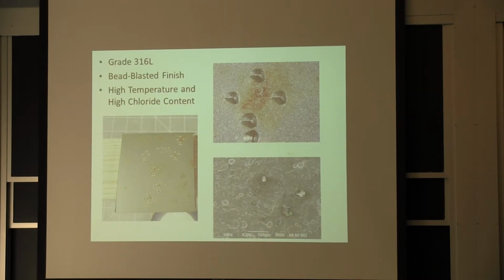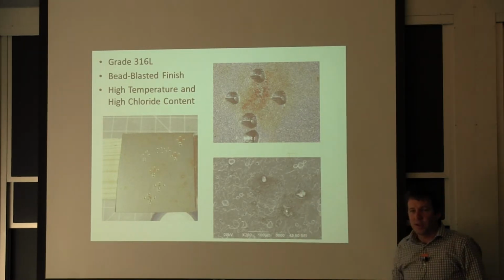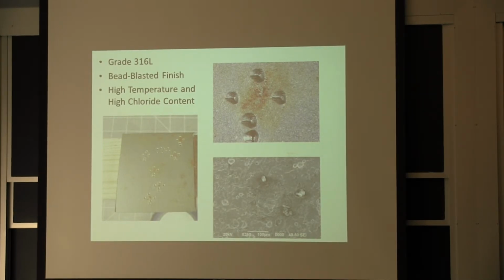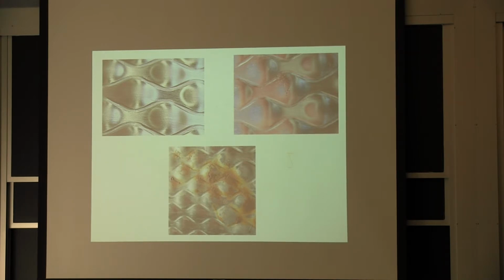This is a more severe issue, these plates. You can see one side wasn't worked on. They were using beads to make a special finish, a kind of satin finish, on the stainless steel. But the beads were so small and provided at high energy that it was creating holes, and they were remaining embedded on the surface, and that caused the initiation of the pitting reaction. And then from there, it just starts growing to a macroscopic size. This is the same thing here, where you have a lot of mechanical work to make that brushed finish on stainless steel. Looks great, but in terms of corrosion resistance, it's reducing it, because now you have a roughness. You already have preferential sites to start the pitting reaction.